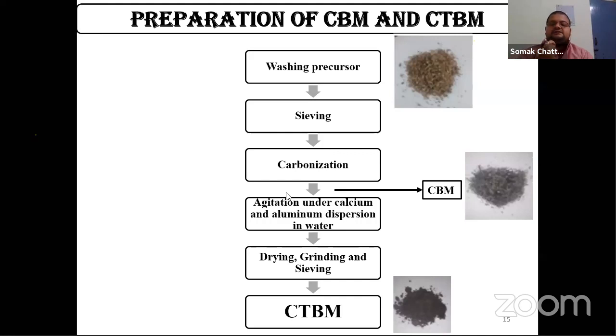So once this carbonization part is over, we will go for agitation in calcium and aluminum dispersion in water. The main reason for calcium is that calcium oxide or calcium hydroxide is used to provide a reverse concentration gradient. Whenever you add aluminum in water, it becomes very acidic, and therefore whatever source of calcium is present within the bone meal might leach out. To restrict the leaching out, we have to provide a reverse concentration gradient, and that is why calcium is used over here.